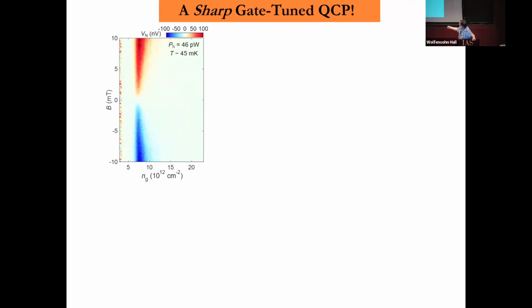So we apply a little bit of field, only a few milli-Tesla, because we still need to see the signal. What really happens is you have no signal, no fluctuation, in the superconducting state. And then you keep reducing density and there's still no fluctuations because you still have a good superconducting state, until suddenly at one point, the fluctuation really develops. So you have a proliferation of vortex and anti-vortex very strongly, and then suddenly, the next moment, it disappears.